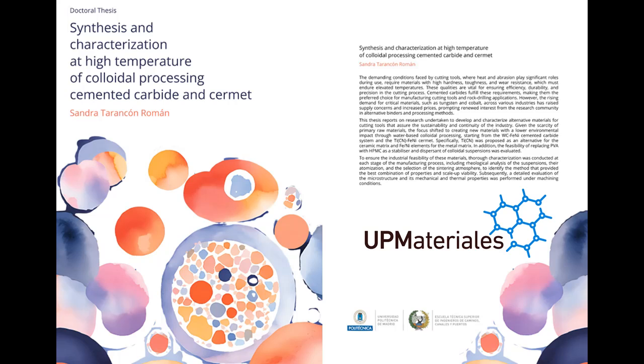I see. And they had to carefully combine these powders in water to create those stable suspensions, right? What were those special additives they used to achieve that? They used deionized water as the base liquid, and then they added specific chemicals to help the particles disperse and remain stable. These included tetramethylammonium hydroxide, TMAH, hydroxypropyl methylcellulose, HPMC, TPMB glycol ether, and polyethylenimine, PEI. Those are some serious tongue twisters, and it sounds like they put a lot of effort into optimizing the proportions of those additives to get the best possible suspension. They did. The thesis mentions that the specific ratios they used were based on previous research. So they weren't starting completely from scratch, which is always helpful in research.